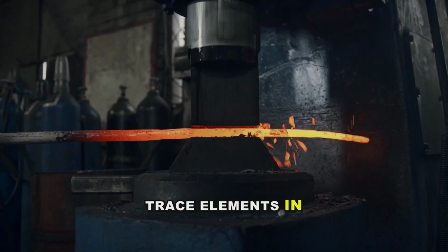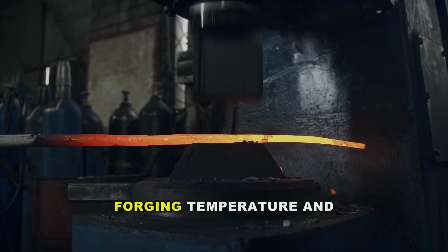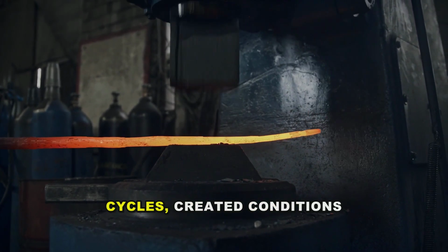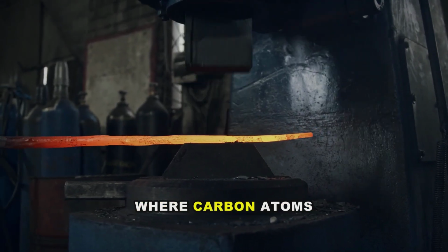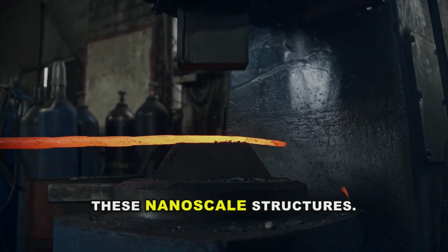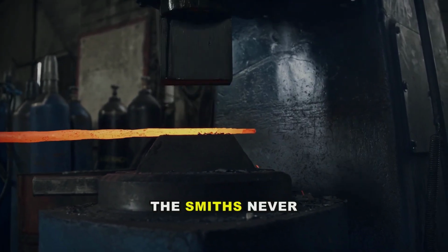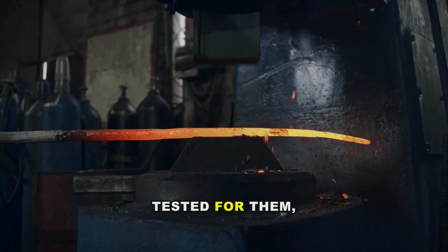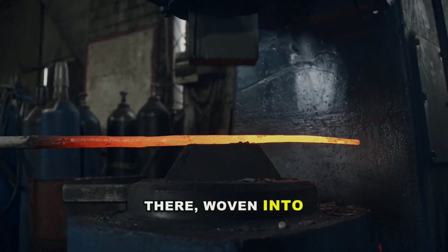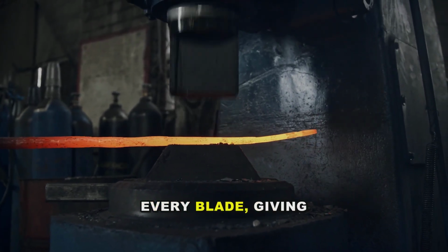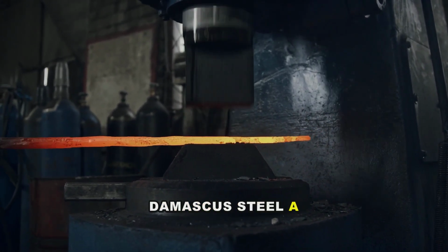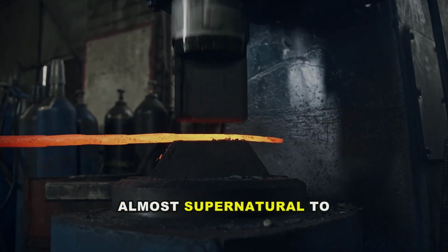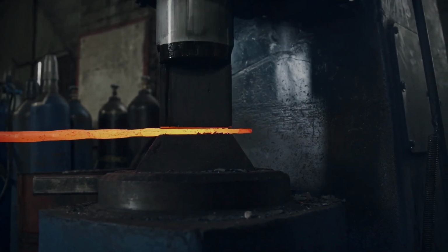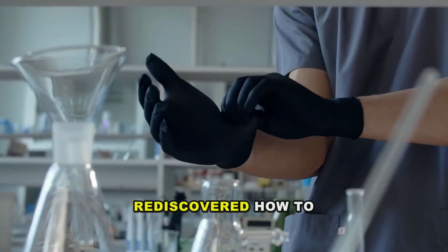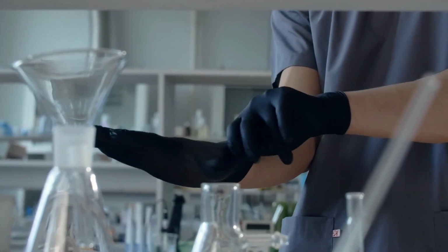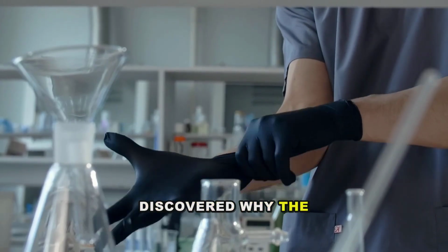The trace elements in the Wootz, combined with the specific forging temperature and the slow cooling cycles, created conditions where carbon atoms assembled themselves into these nanoscale structures. The smiths never saw them, never tested for them, but they were there, woven into the microstructure of every blade, giving Damascus steel a toughness that seemed almost supernatural to anyone who fought against it. Pendray and Verhoeven had rediscovered how to make the patterns. Reibold and Paufler discovered why the blades were so good.